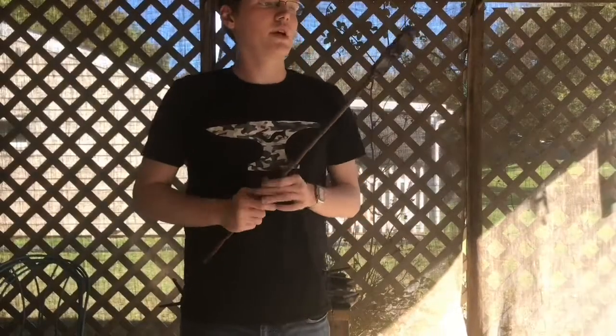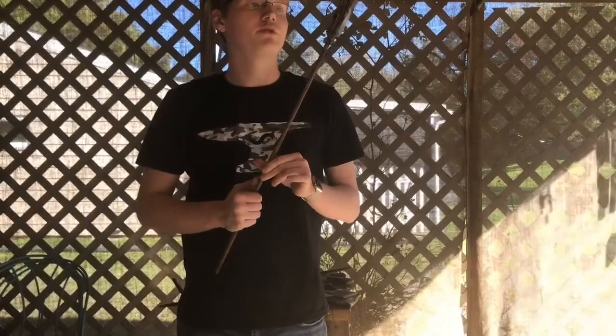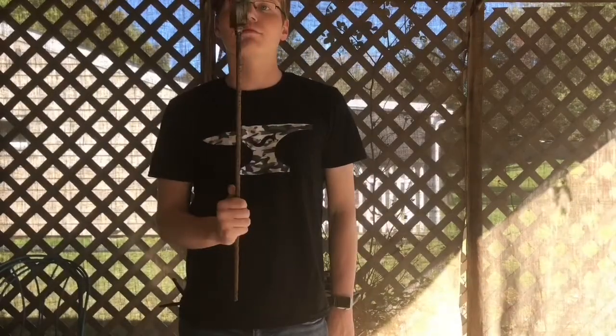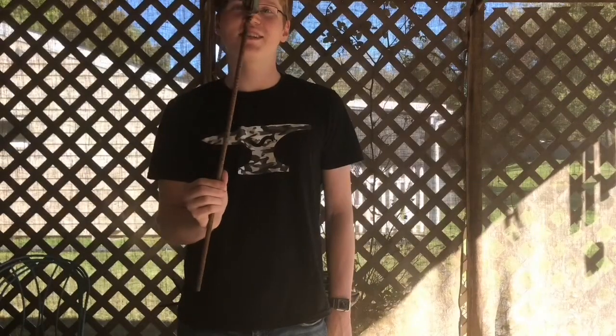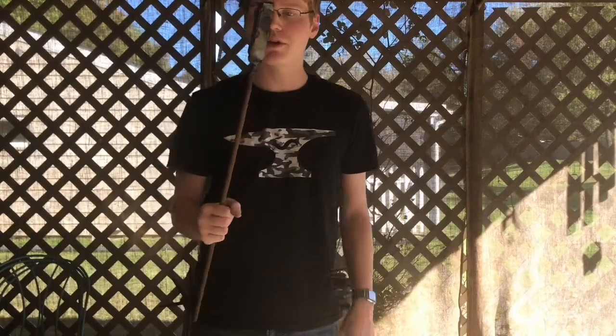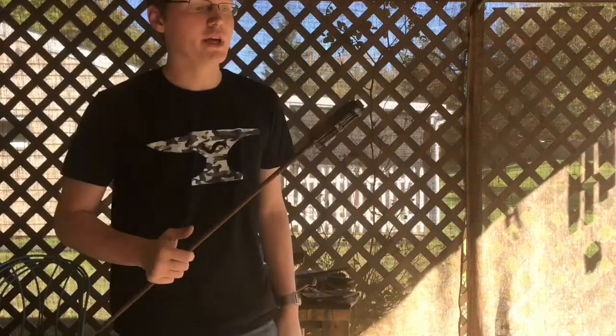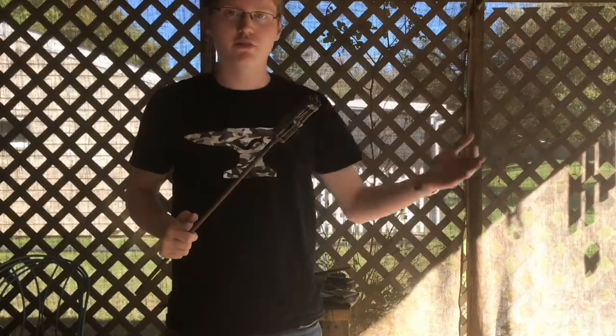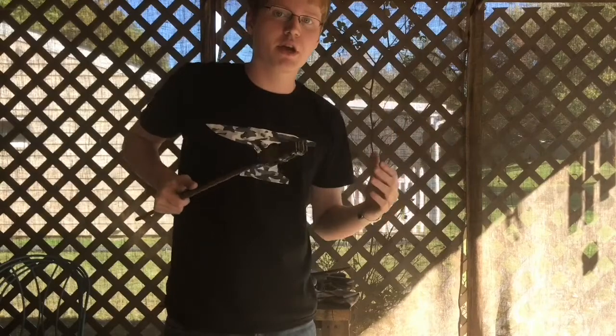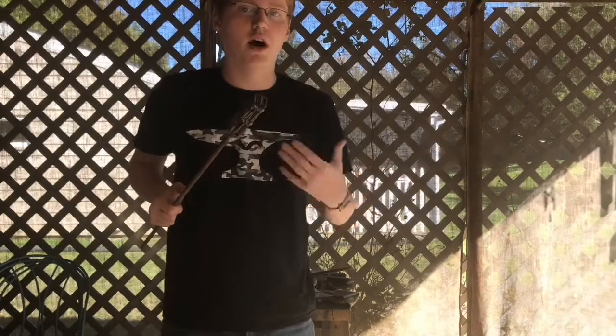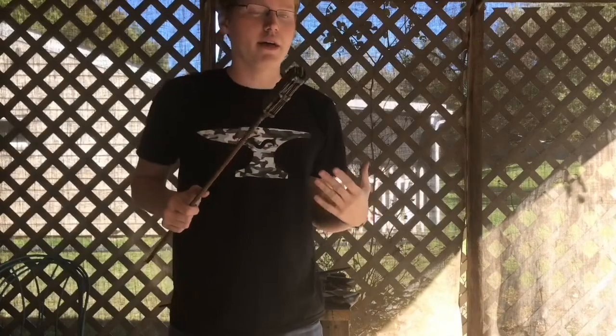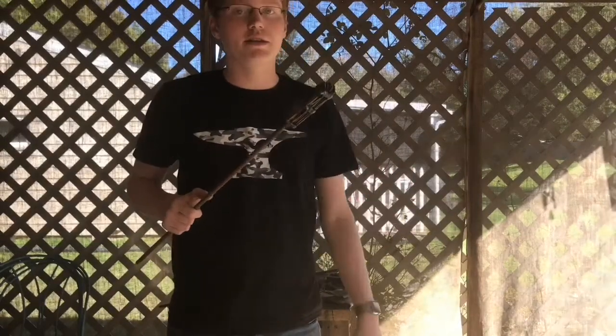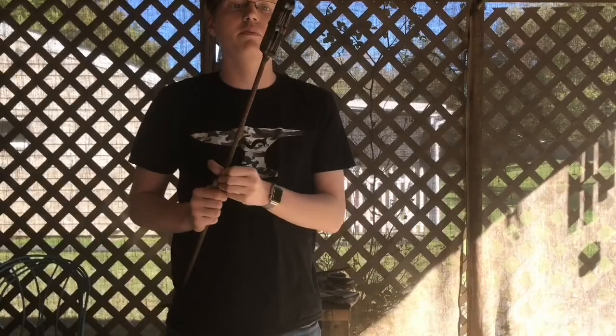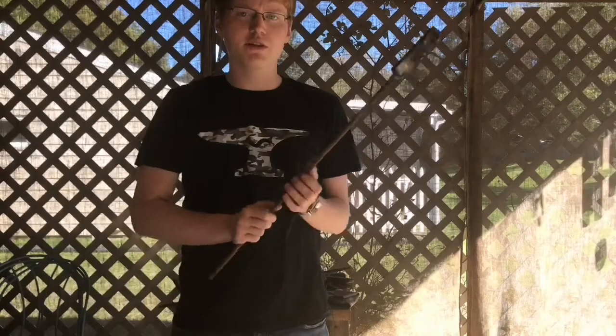So now I have this really nicely welded up stack of saw blade parts, strips. So now what we're going to do is put it into the forge, heat it up to about 1800 degrees, sprinkle some borax flux on it. That'll help get in between the layers and purge it of oxygen and any sort of oxides that form on the steel as it's heating up from the forge and from welding. And then we're going to heat it up to around 2400 to 2600 degrees Fahrenheit.